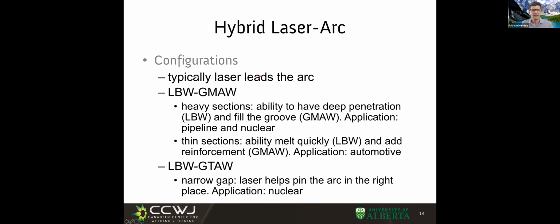Typically, the laser leads the arc, and it would be the case of laser MIG or laser TIG. And in this case, what we have is that we can have the best of both worlds. The laser can give us the depth, and the MIG can give us a bridging of the gap.